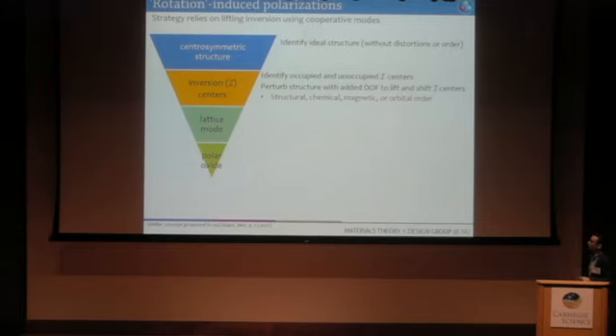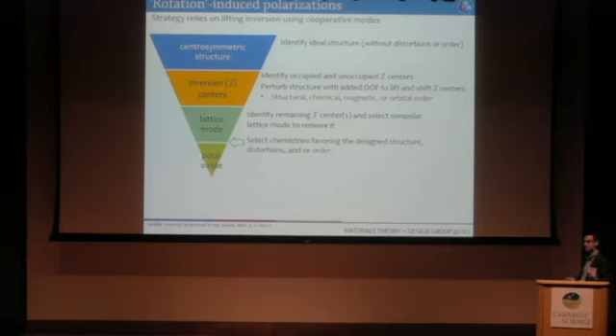Or it could be orbital order, and this is going to have the consequence that it either by itself lifts inversion symmetry or it simply shifts the location of the inversion center in the crystal. And so there will be remaining positions for inversion symmetry, and you add one additional degree of freedom or one additional feature, and that will lift inversion.